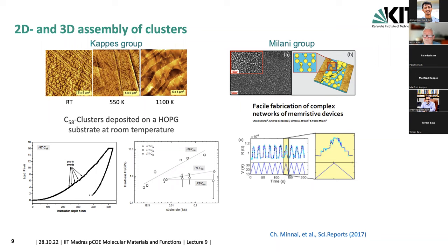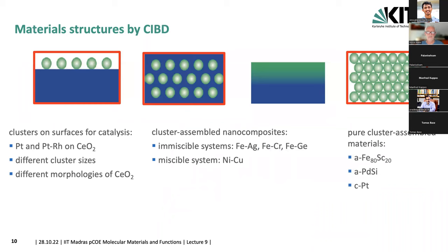Another example from the group of Milani was a complex network of memristive devices, which in this case also consisted of clusters embedded into a matrix. Then you can get a particular dependence of the resistance as a function of the voltage which you apply, and this could be used for memristor applications. So there are some studies on either purely cluster deposited materials and their mechanical properties, or here a functional property of a nanocomposite material, which in this case had less control of the particle size than what I would like to do. Anyway, here is this again with different material systems, but I have mentioned that already.